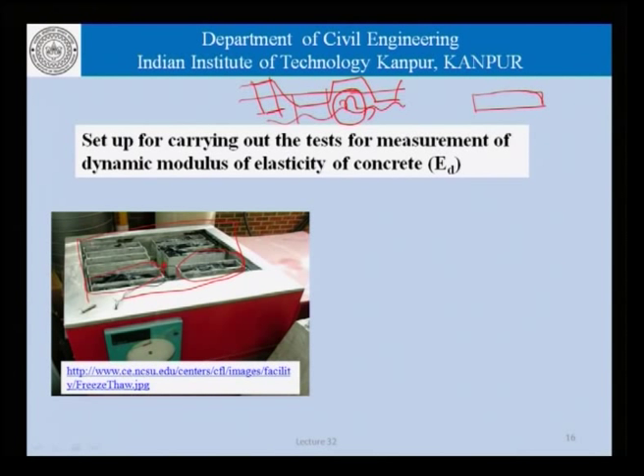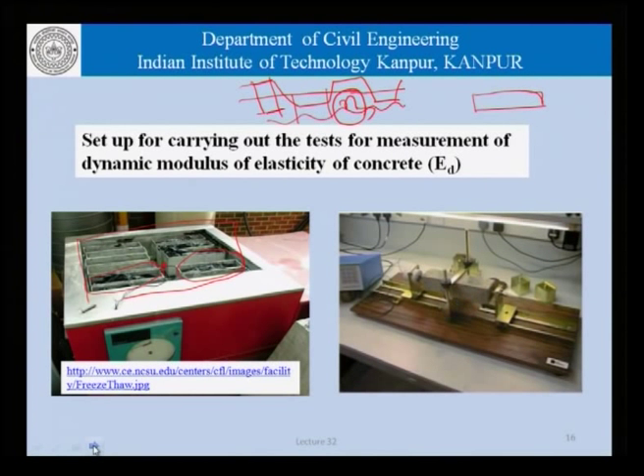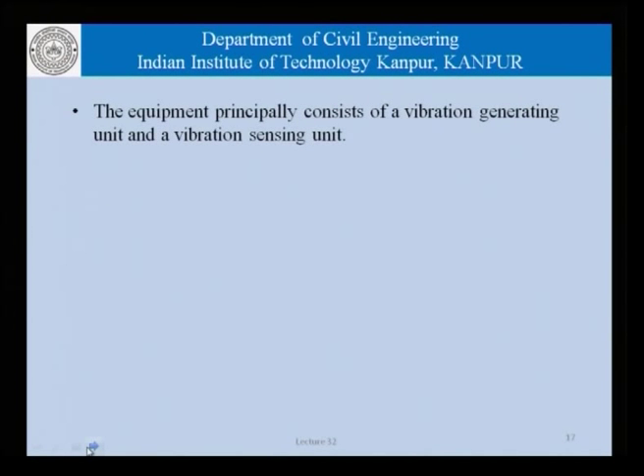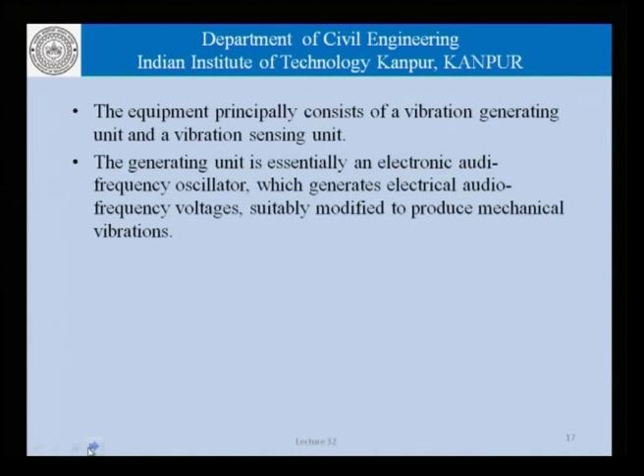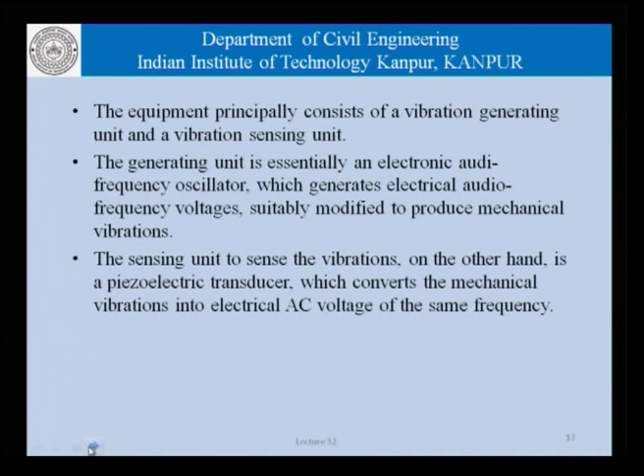Exposing these concrete specimens to this regime of varying temperatures, we subject them to deterioration, and while the test is being done, at different points in time, we estimate the modulus of elasticity using a setup which is something like this. This setup basically consists of a vibration generating unit and a vibration sensing unit. The generating unit is essentially an electronic audio frequency oscillator, which generates electrical audio frequency voltages suitably modified to produce mechanical vibrations in the concrete specimen. On the sensing side, we have a piezoelectric transducer, which converts the mechanical vibrations into electrical AC voltages of the same frequency.